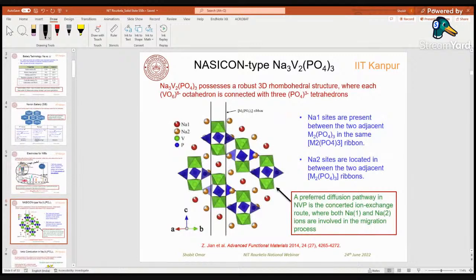And here is the structure of Na3V2(PO4)3, and you can see vanadium is forming an octahedron like this, while phosphorus is forming a tetrahedron, right? And each octahedron is connected to 6 tetrahedra, right? And there are 2 sodium sites in the NASICON structure of Na3V2(PO4)3, which are known as Na1 and Na2. These are 2 crystallographically different sites. Okay, they are not equivalent.